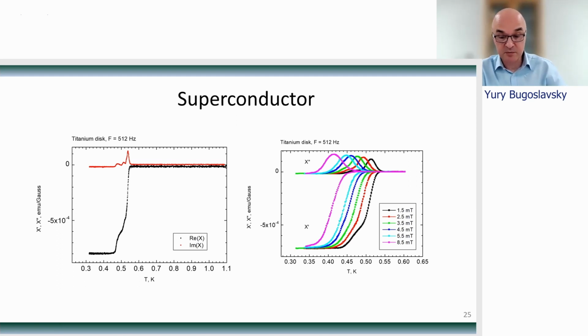One particular example where this method produces beautiful and informative data is in studies of superconductors. The example I show here is the superconducting transition in titanium, which happens at the temperature of 550 millikelvin. To make this measurement, we combined a small AC susceptometer with our helium-3 refrigerator. You can see that at temperature below the superconducting transition, which is here, from 0.3 Kelvin to 0.5 Kelvin, the sample is perfectly diamagnetic. And for that reason, it has negative real part of AC susceptibility, shown here in the black curve. As we approach the transition, the real part of susceptibility drops sharply to 0.